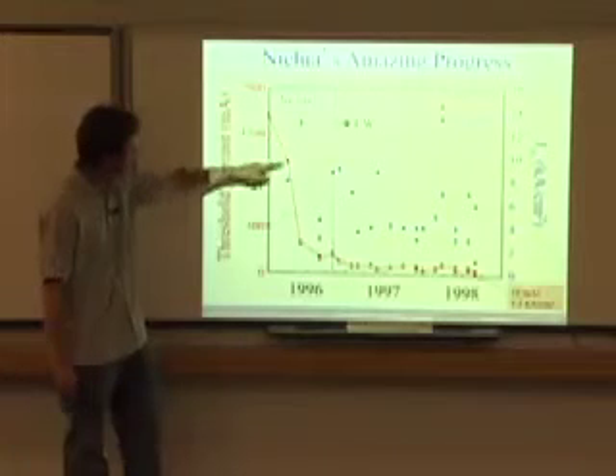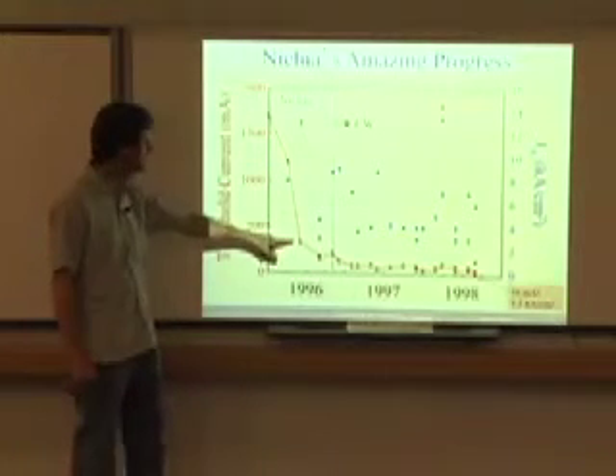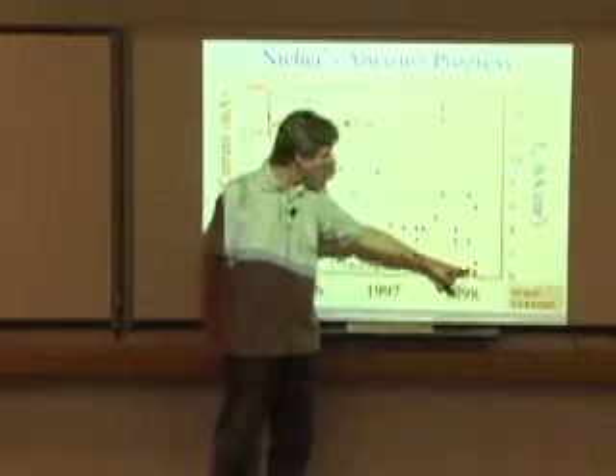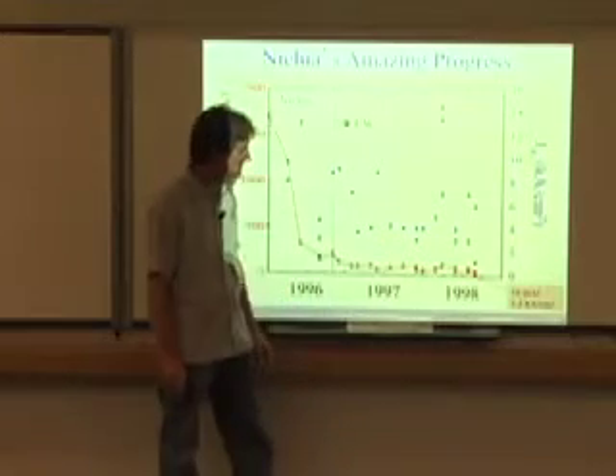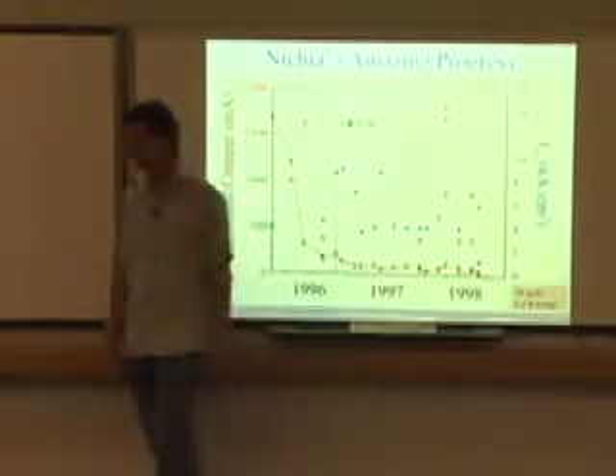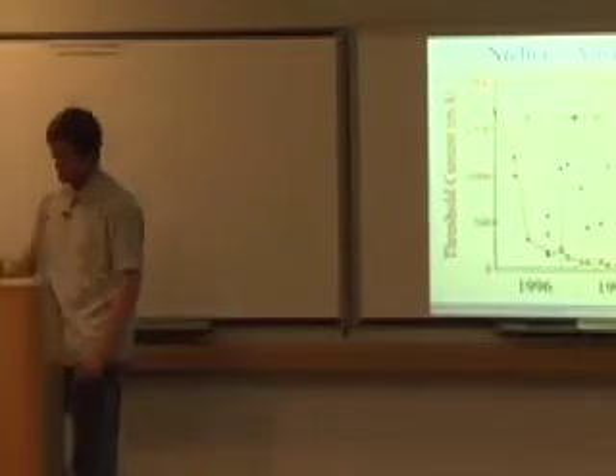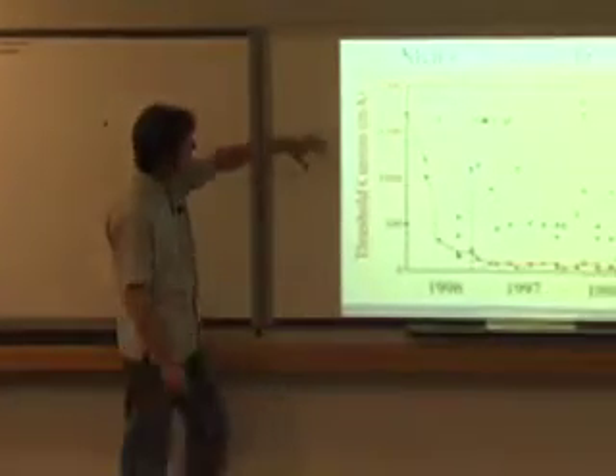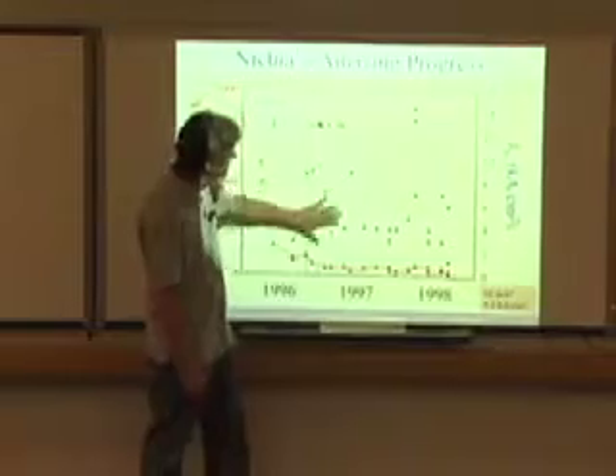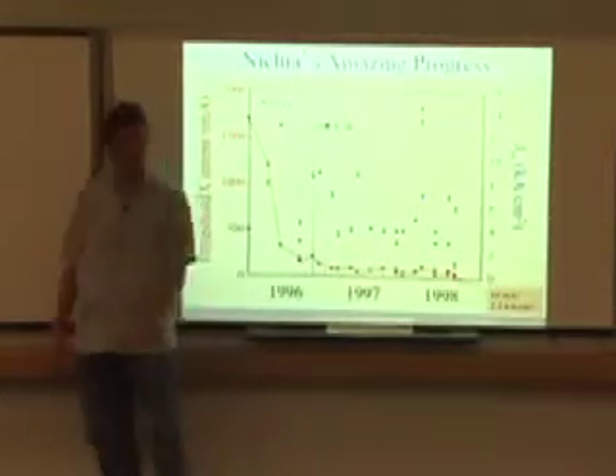Because it went from 1.7 amps down to 350 milliamps, and then by the middle of 1998, you're down at a 16 milliamp threshold, 1.2 kiloamps per centimeter squared, which is just crazy in a 2-year time period. In addition, threshold current densities stayed around here, a little noisy, but in the end dropped way down.